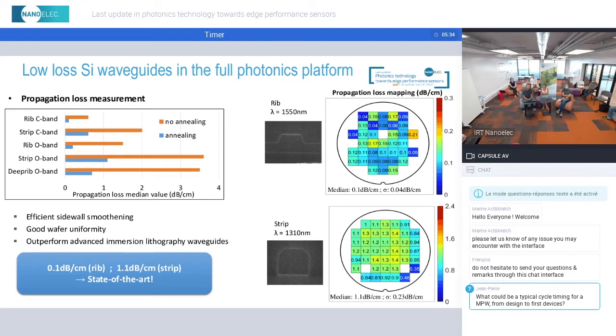1.1 dB per centimeter for the median value and 0.2 for the standard deviation. So it's a very good result in terms of propagation loss. It means the process is very efficient to reduce the roughness of the sidewall. We have very good wafer uniformity, and we are better than what we can obtain with immersion lithography patterning. Those results, for example, 0.1 dB per centimeter in the C band and 1.1 dB per centimeter for strip waveguide in the O band, are at the state of the art in terms of propagation loss.